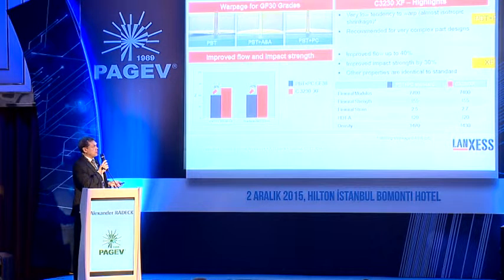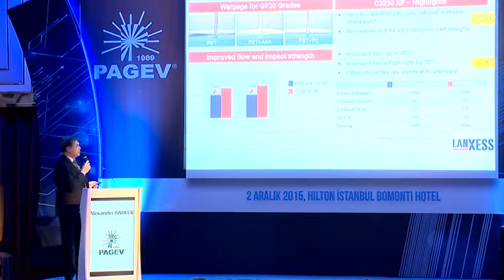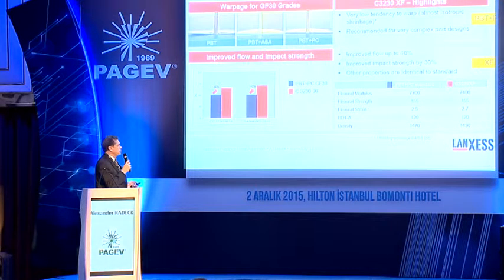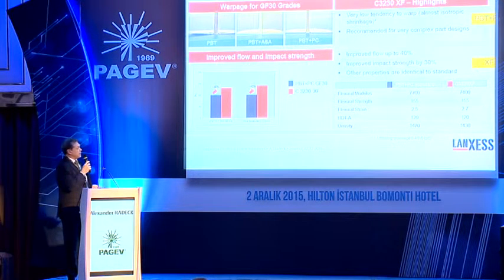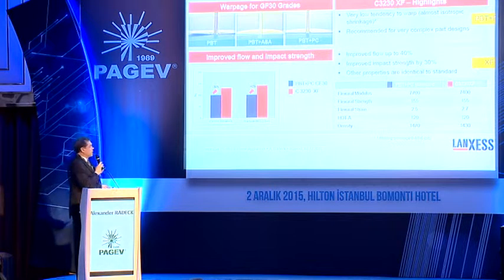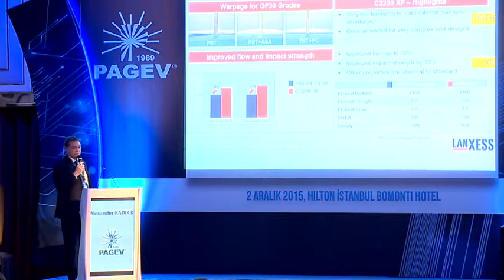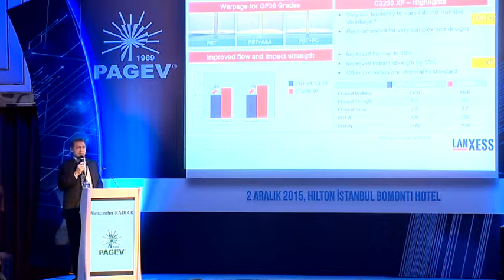With the easy flow additive, we could improve the flowability by up to 40%. Okay, that is a theoretical value determined by a flow spiral at a wall thickness of 2.5 millimeter, and can only be an indication that may be different at different wall thicknesses. But we also achieve an improvement in the impact strength by 30%, and that is because we have a very good bonding of the easy flow additive to the polymer matrix. All other properties are identical to the standard grade without easy flow package. And a nice side effect is that with the easy flow version you have even a lower density compared to the standard.